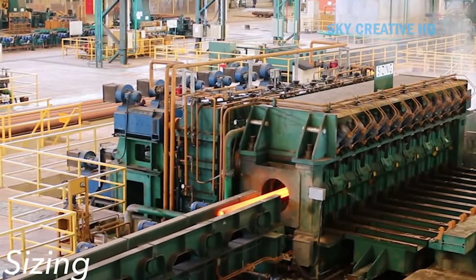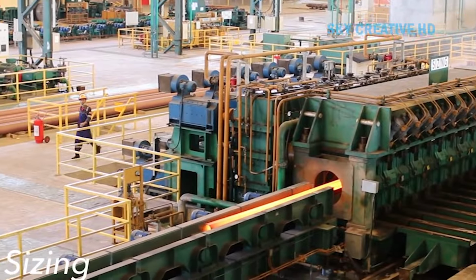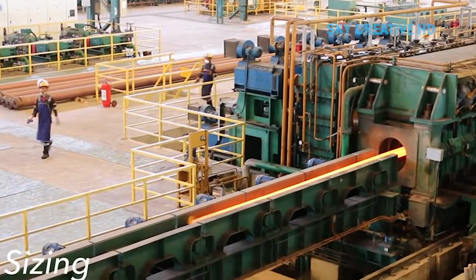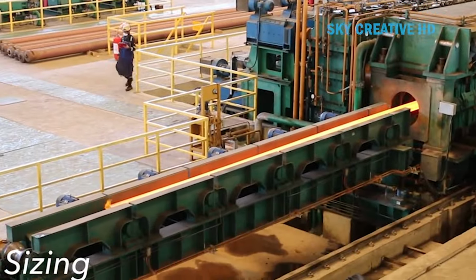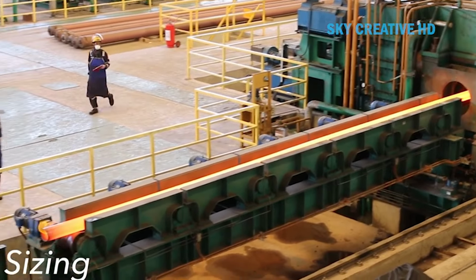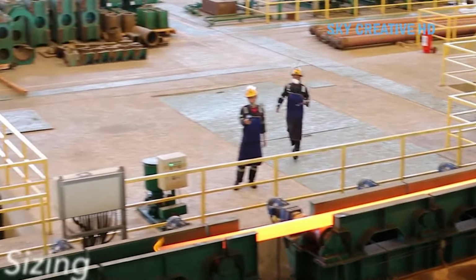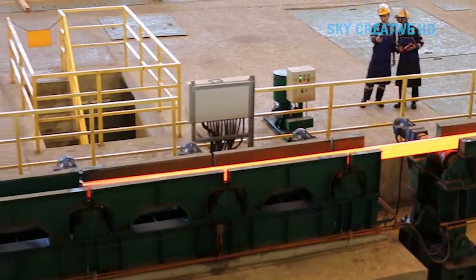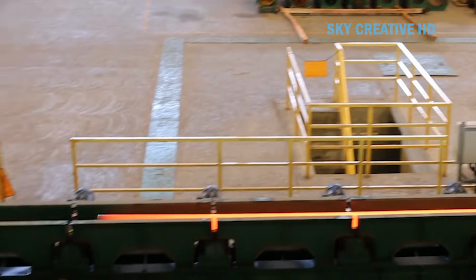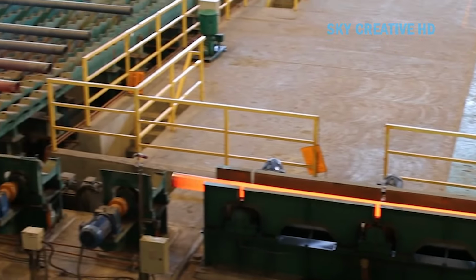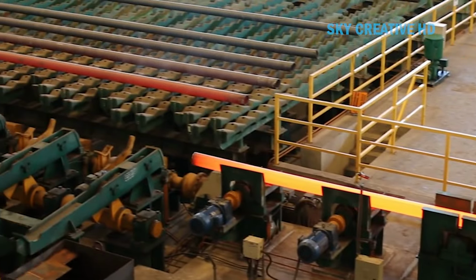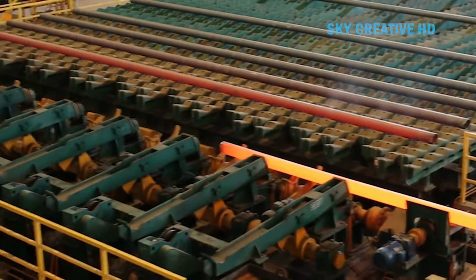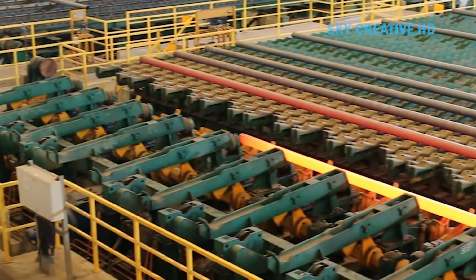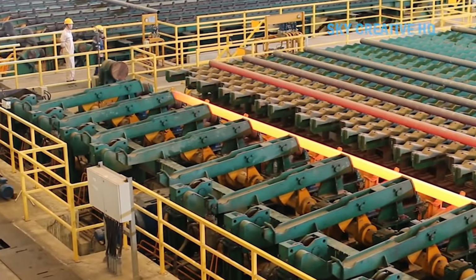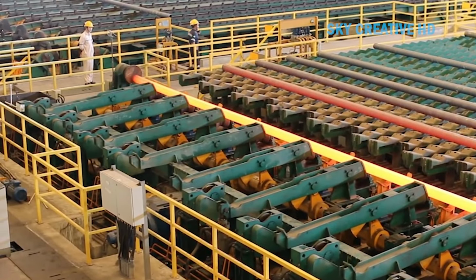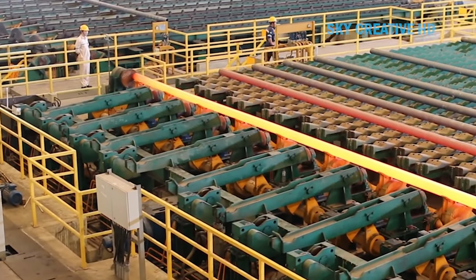After this hot forming process, the pipe enters a stretch-reducing mill, a series of stands, sometimes 40 or more, that gradually reduce the outside diameter while the pipe is still hot but cooling. Each stand has grooved rolls that work the pipe slightly smaller. The pipe travels through at impressive speeds, sometimes over 20 feet per second, with cooling water sprays between stands controlling the temperature profile. The pipe then moves to the cooling bed, a long section where pipes are laid out to cool uniformly. Proper cooling is crucial because it affects the pipe's metallurgical properties and prevents warping.